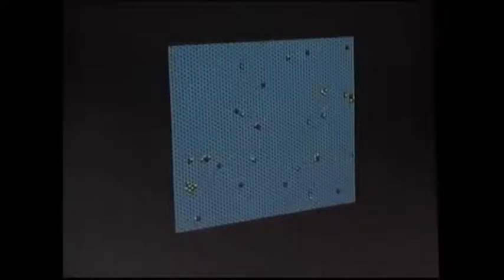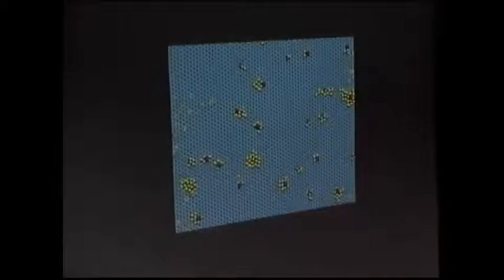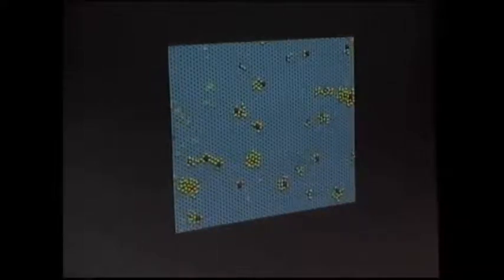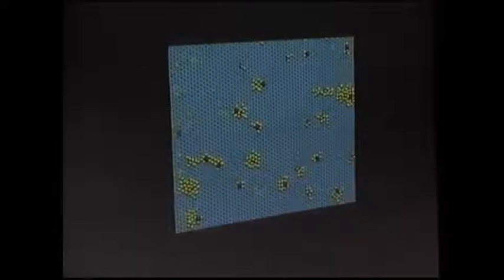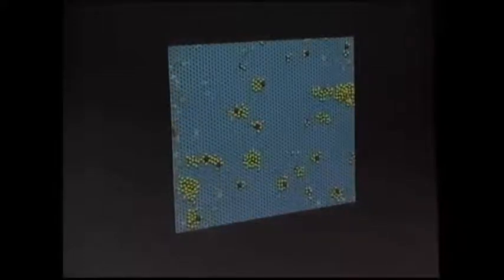Here, the idea is that we fluorinated the graphene membrane first, and then later we released only hydrogen into the chamber. Then we see that the hydrogens attach almost exclusively close to the fluorines. That's the idea of catalyzation of hydrogen capturing by the fluorine. Okay. We see big domains here. Right.